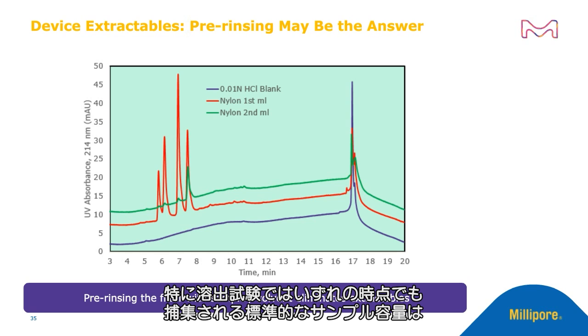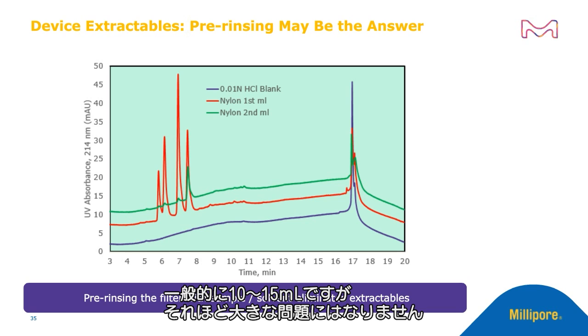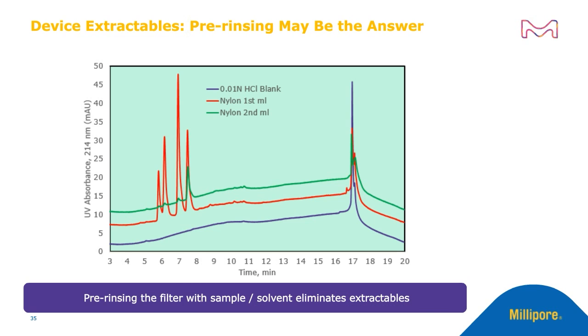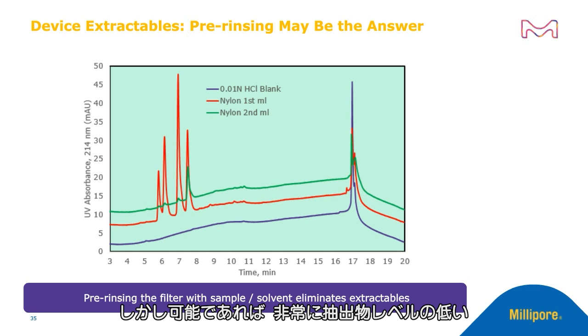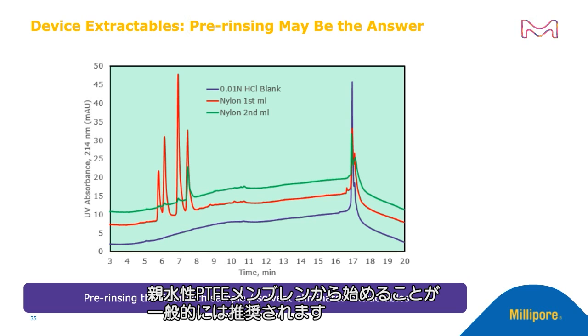Especially with dissolution testing, where the typical sample volume collected at any time point is generally 10 to 15 ml, this should not be a big problem. But it is generally preferred if we can use a hydrophilic PTFE membrane, which has very, very low levels of extractables to begin with.